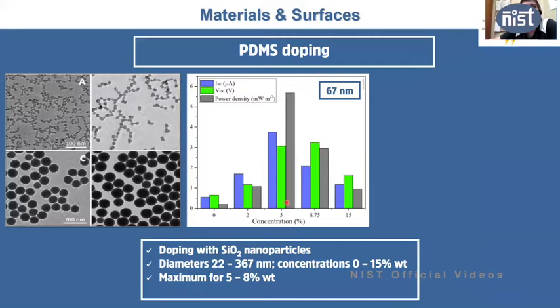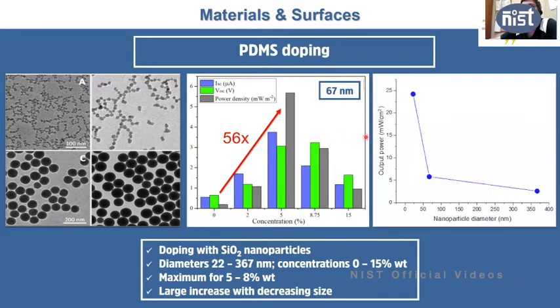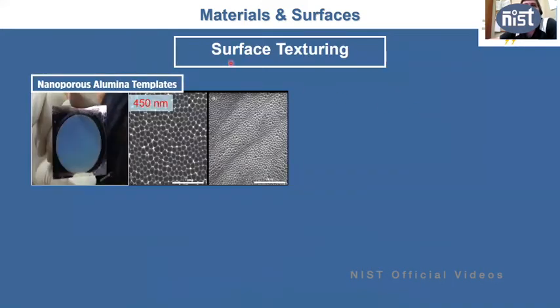As soon as these nanoparticles come to the surface, you stop having an increase of the power output, and then you have an output decrease. So if you change just the concentration a little bit, by 5% using nanoparticles of silica, you can get a 56-time increase on the power density that you obtain. It also depends on the nanoparticle diameter. You can get higher output voltages by doping the PDMS material with smaller nanoparticles. And we believe that this is related to the differences in the dielectric constant of these nanoparticles as the size goes down. You can also do surface texturing, so you can change the surface of your material by different